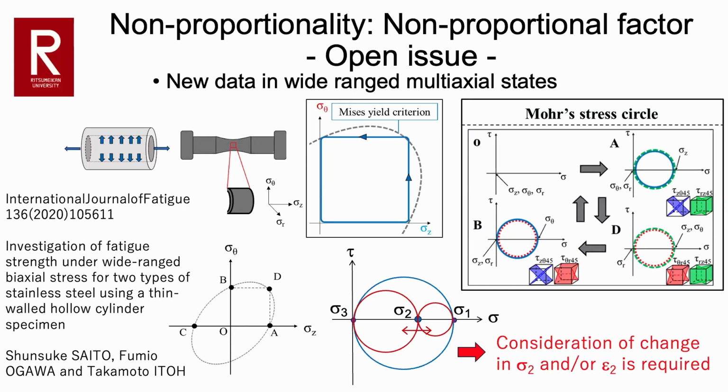At the points O, A, D, B on the path, this maximum plane is changed. In that case, we could see the additional hardening, not so large. We could see the additional hardening and also the reduction in failure life. So damage is increased. In the previous definition I did not take care of this effect, but the experimental results show the reduction in failure life.